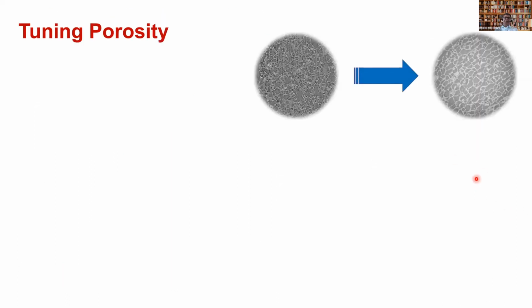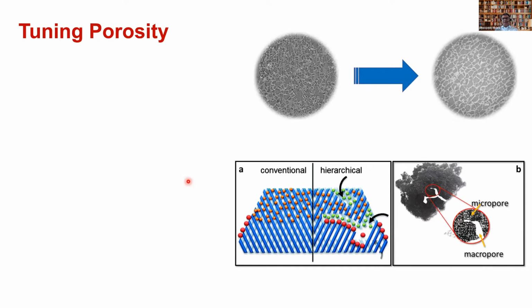So next, I was talking about tuning porosity as a physical method, and this kind of work has also gained a lot of momentum recently. How can we not just tune porosity, but develop hierarchical pore structures within carbon materials? Carbon materials are considered porous materials, perfectly fine, wonderful, but they already have an inherent porous structure. Now, if only we could impose a hierarchical pore structure such that we have macropores, and within those macropores we have mesopores and micropores, we can have very strong active sites. And not only that, we can also have very controlled diffusion, or other kinds of